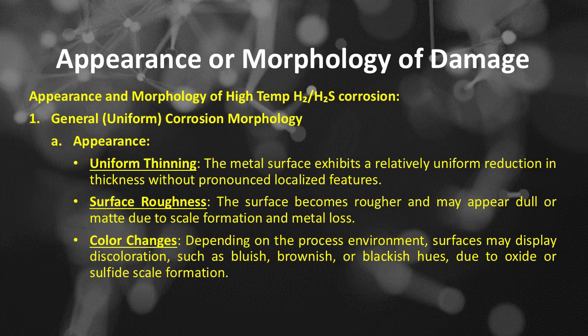The appearance of general or uniform corrosion includes uniform thinning. The metal surface exhibits a relatively uniform reduction in thickness without pronounced localized features. Surface roughness. The surface becomes rougher and may appear dull or matte due to scale formation and metal loss. Color changes. Depending on the process environment, surfaces may display discoloration, such as bluish, brownish, or blackish hues, due to oxide or sulfide scale formation.